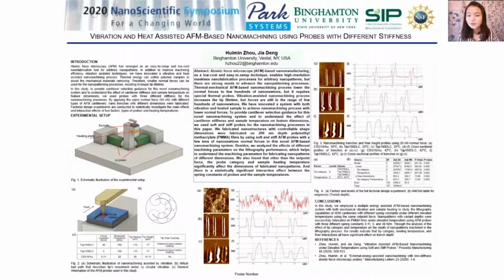In this study, we focused on investigating the effect of different types of AFM probes and different heating temperatures on the lithography performance. We conducted a full factorial experiment. There are 2 factors, tip category and sample temperature. The sample we used is a silicon substrate spin-coated with 200 nanometer thickness PMMA film.